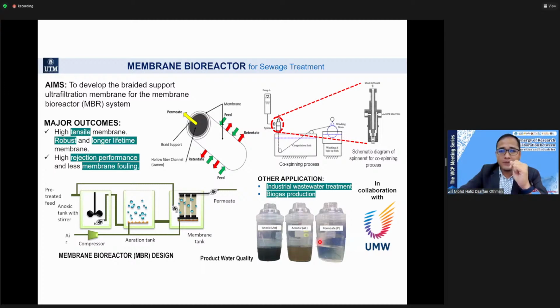We use this hollow fiber polymeric membrane for a membrane bioreactor, but we try to propose a new idea where we put in a braided support in order to enhance the mechanical strength of the membrane, because we know that the polymeric membrane, as I mentioned, when compared with ceramic membrane, has an issue with mechanical strength. So in order to improve it, we add the braided support. Therefore, it can be used for longer operation. Currently, we also have an ongoing project with UMW.